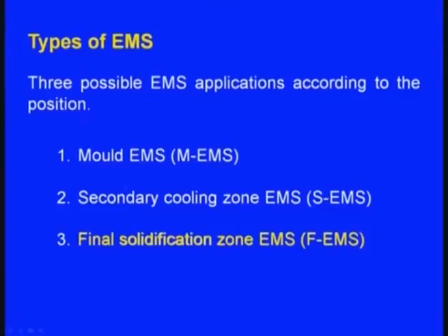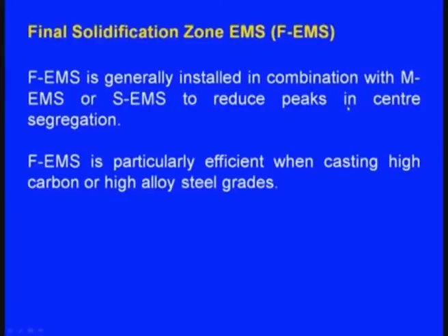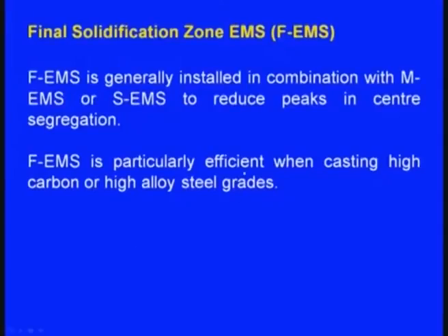So, we have completed the first two. Now, finally, let us see the third one, that is the final solidification zone EMS, FEMS. FEMS is generally installed in combination with MEMS or SEMS to reduce peaks in center segregation. So, if we want to apply FEMS, prior to that we should have used either MEMS or SEMS. FEMS is particularly efficient when casting high carbon or high alloy steel grades.